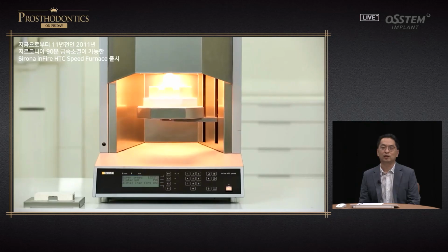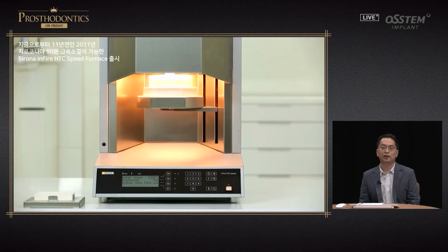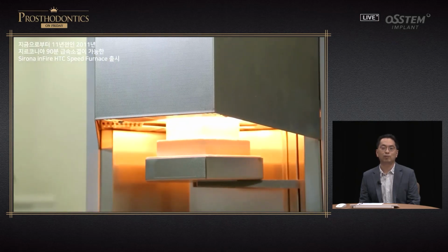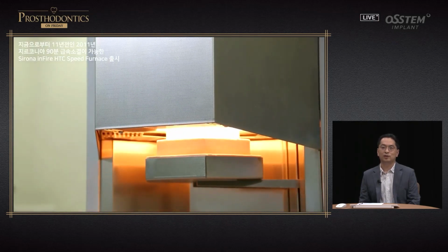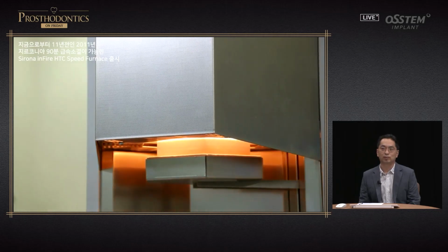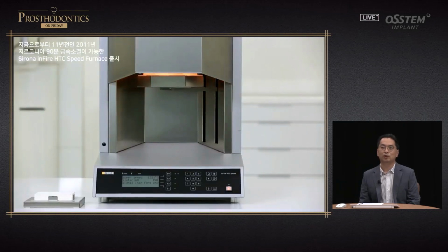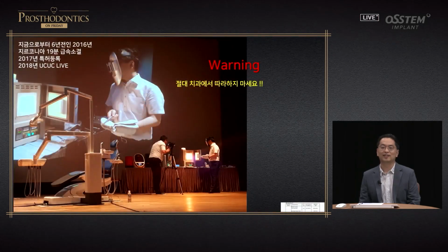If you use it clinically, at times this led to zirconia fracture, and at times it didn't, so there were a lot of uncertainty. Therefore, it was not widely adopted. However, I was inspired by this idea. At the time, I only had this average furnace. About 6 years ago, in 2016, I used a normal furnace to do rapid zirconia sintering.